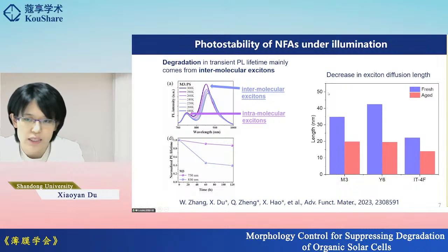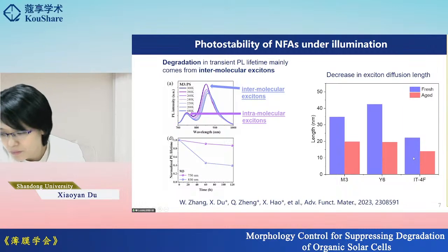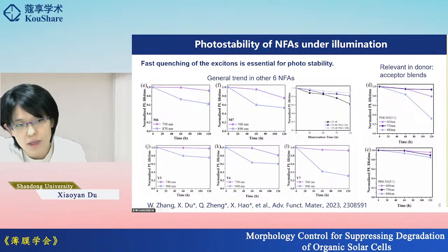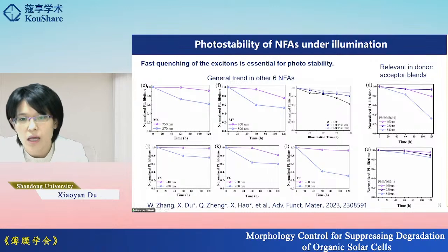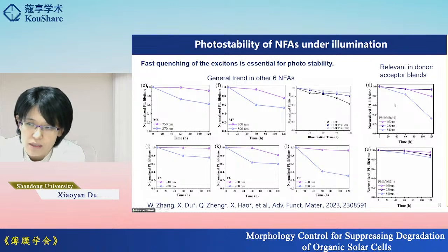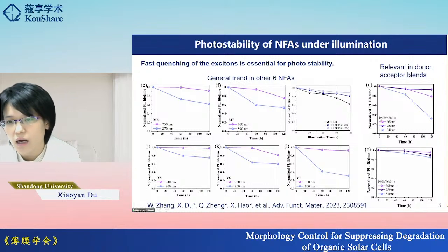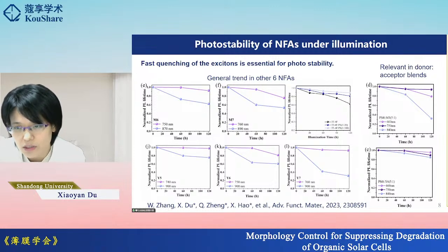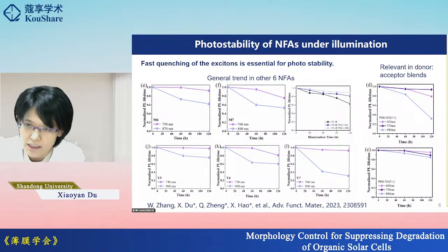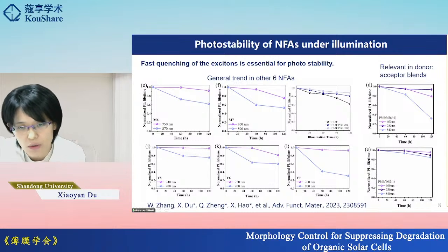And these results correlate with the decrease in the exciton diffusion length, as shown here in three of the materials. And this trend is observed in all the other six non-fullerene acceptors, including the other two M-series materials, the three Y-series materials, and also the IT series materials. And we also see relevance of this phenomenon in the blend films with the commonly used donor material here. So this is quite a general phenomenon for the degradation of exciton lifetime and diffusion length in the aggregated states. Although we are not quite sure now how to overcome this or what the origin is, we could